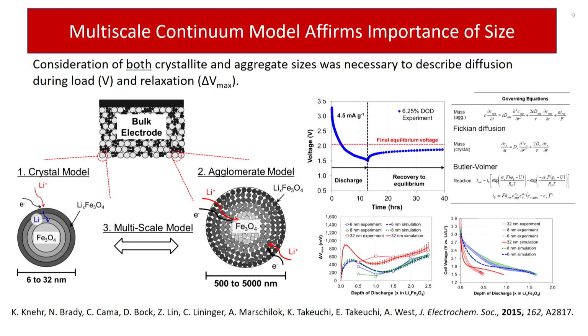In order to develop a model that fully represents the voltage profiles of these systems, both the crystal model and the agglomerate model must be combined into a true multi-scale model. And he can predict, depending upon what rate you're using, what crystal size you need. The goal ultimately is to minimize agglomeration because it creates a second limitation to transport within the electrode.